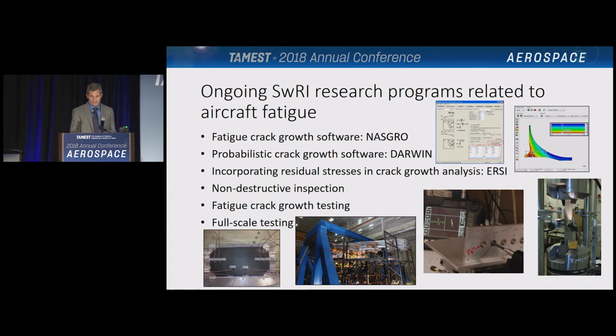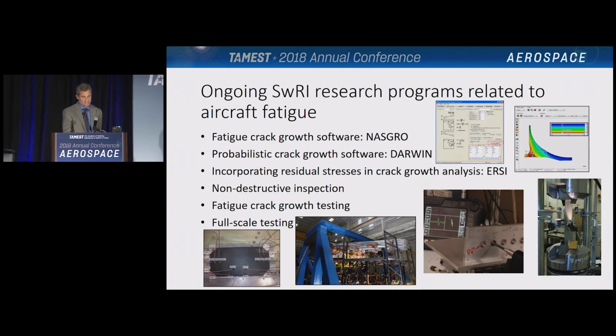The third is ERSI, or Engineered Residual Stress Implementation, which is a working group developed for incorporating residual stresses into these types of crack growth analyses. We're also working on developing inspection methods to find smaller and smaller flaws in structures, such as this method right there for looking through bushings into the second layer structure for cracks using low-frequency eddy current.